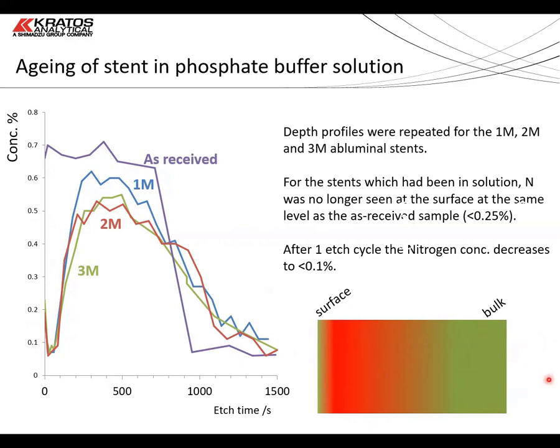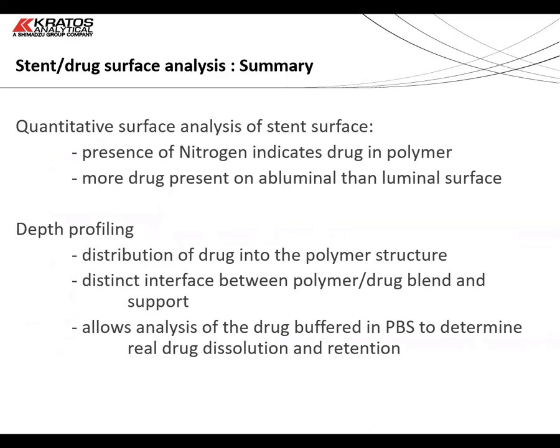the material. So in conclusion, we have shown that XPS is suited to characterization of these drug-coated polymer stents. The nitrogen that is present in the drug polymer blend and not the polymer stent support material acts as the marker for the drug. This allows a quantitative study concluding that there is more drug material on the outer abluminal than inner luminal surfaces. The abluminal surface of the as-manufactured stent was fully characterized for drug concentration, layer thickness, and drug distribution. Aging experiments were performed to see the dissolution of the drug from the stent into the PBS.